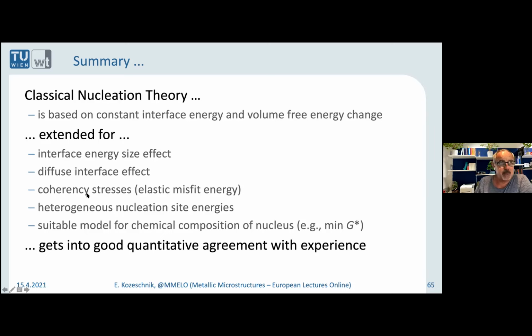Yeah, so there's one example that we published many years ago for the aluminum nitride precipitation in steel, where we could clearly show that homogeneous nucleation of aluminum nitrides in the crystal is practically impossible. And you need very high supersaturation to nucleate on these locations. And that was possible by the proper prediction of the coherency energy, this coherency stress elastic misfit energy. What was new, and what's not so well known in the community, is how to take into account the nucleation site energies of grain boundaries or grain boundary corners. So we are going to publish that soon, and let's see what the referees say.